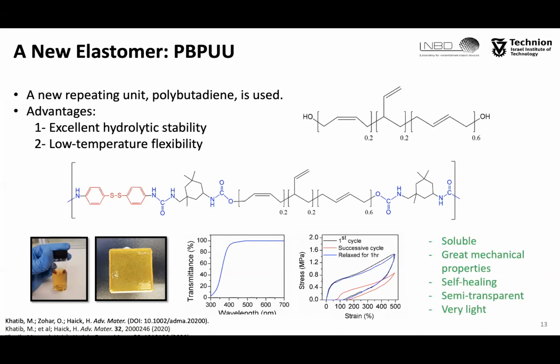For this purpose, we synthesized a new polymer from hydroxyl terminated polybutadiene, which we abbreviate HTPB, extended by isophorone diisocyanate and 4-aminophenyl disulfide through two main reactions, which you can see here in the middle of the slide.